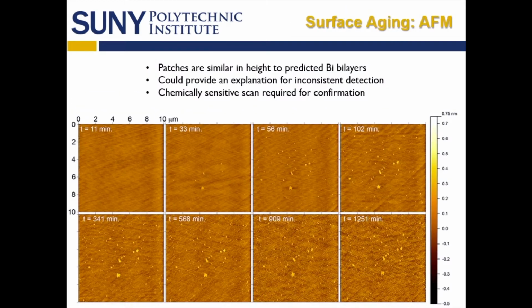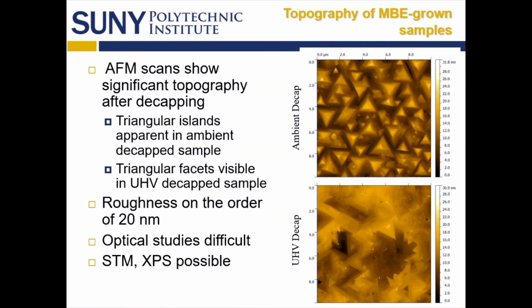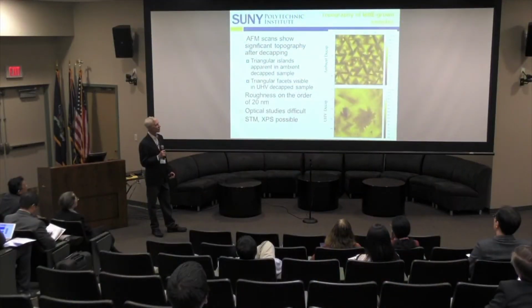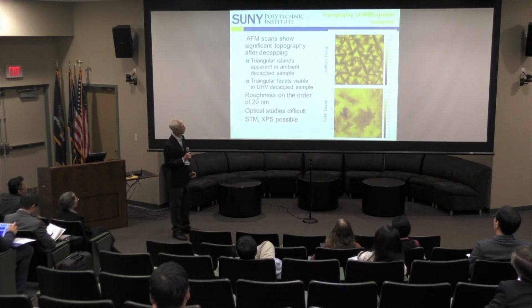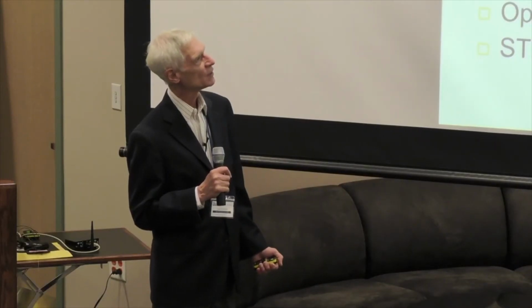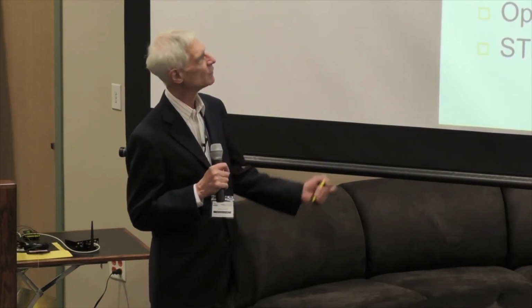But curiously, when we looked at the surface in an AFM study, and you've got to give Avery some credit for being incredibly patient, he took AFM data of the surface and observed these little clumps forming with time. That was something that was very difficult to observe any other way. Interesting. So even though the oxidation doesn't show a change, the AFM showed a change in the surface. The guess was those were clumps of bismuth bilayers that had agglomerated and gone to the surface. It turns out that bismuth selenide is more air sensitive than many believe.